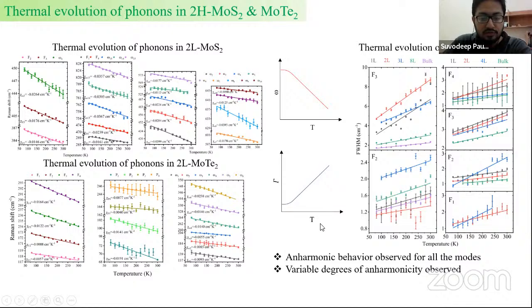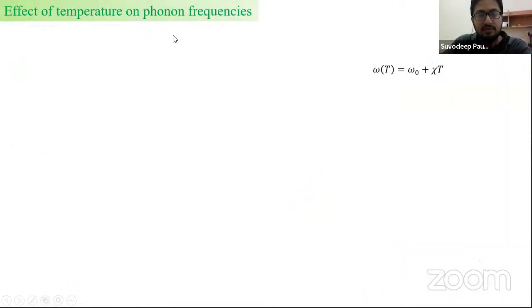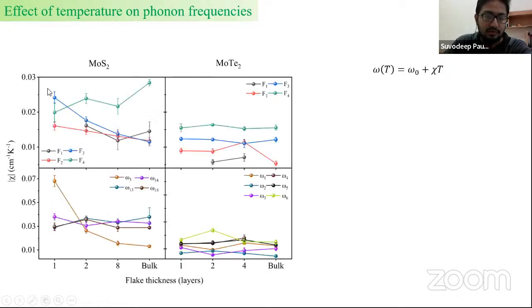Now what we would be interested in is to see the strength of the anharmonicity and its dependence on various parameters. So first, we would see the effect of temperature on the phonon frequencies. As we saw, the phonon frequencies show redshift with temperature. So this is the linear equation we fit it with, and we obtain the negative slopes of the curves, which give us the strength of the anharmonicity.